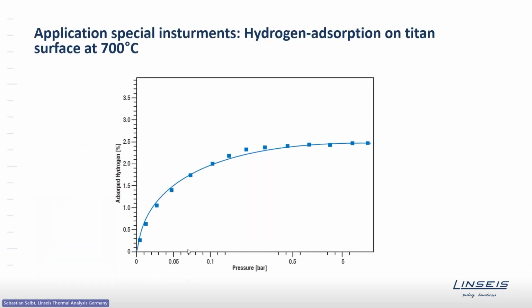Just one application to show. This is a sorption measurement and the pressure balance. So this is the sorption of hydrogen on a titanium surface at 700 centigrade isothermal segment. This experiment was carried out at different pressures, beginning at 10^-3 millibars and then increasing the pressure step by step. So the experiment was performed at different pressure steps. And you can see here, at a certain pressure level, you reach a saturation. So already at 0.5 bars, you reach saturation. The amount of hydrogen that will be sorbed by the surface will not increase anymore, even if you go up to 5 bars. And such experiments help you to find saturation levels and the maximum of possible sorbed hydrogen or any other gas on a sorbent that you can use. But as said, I will not focus that much on the special versions.